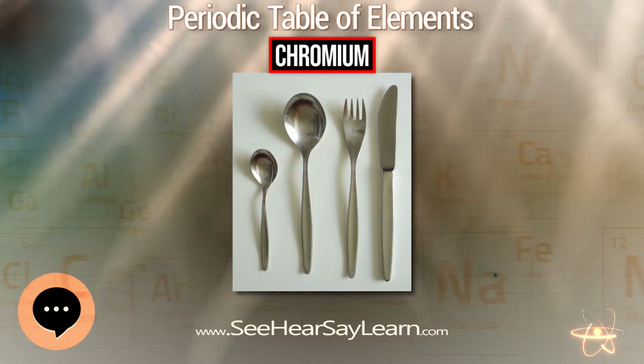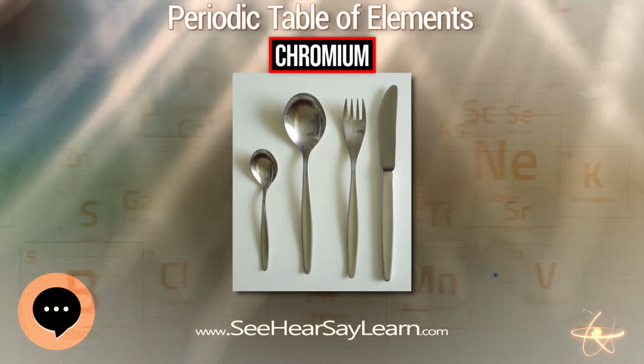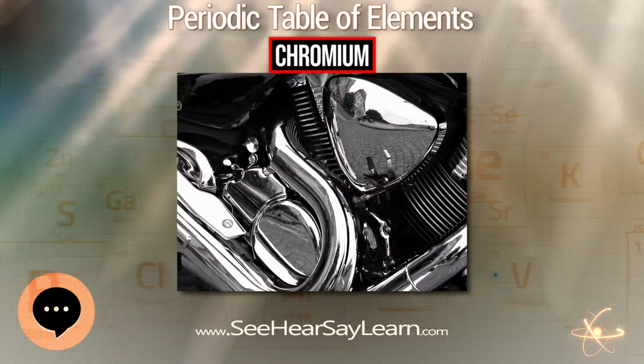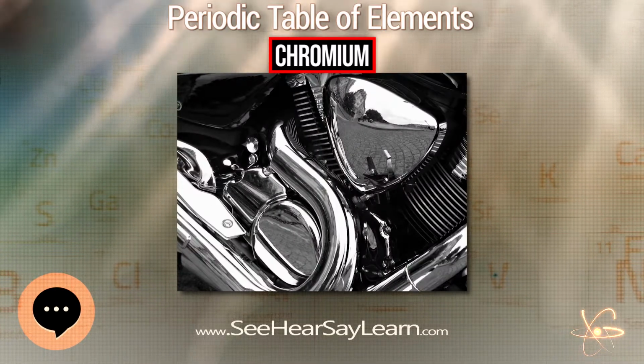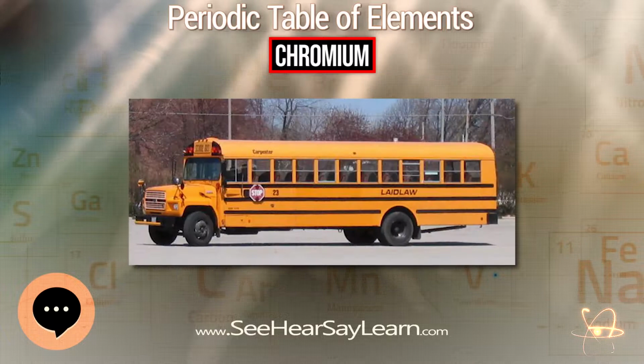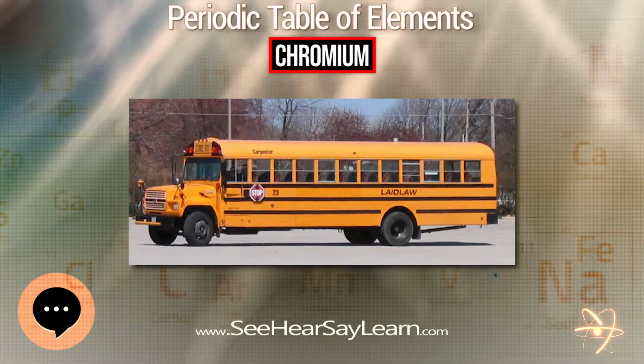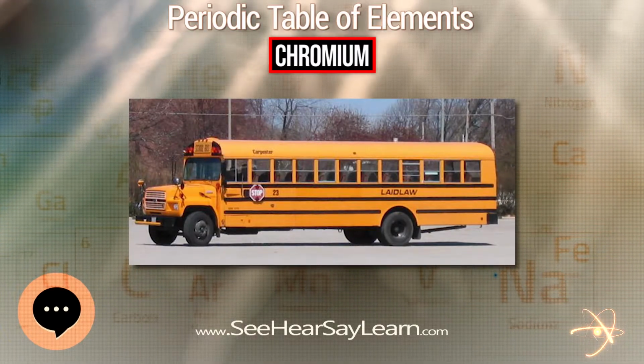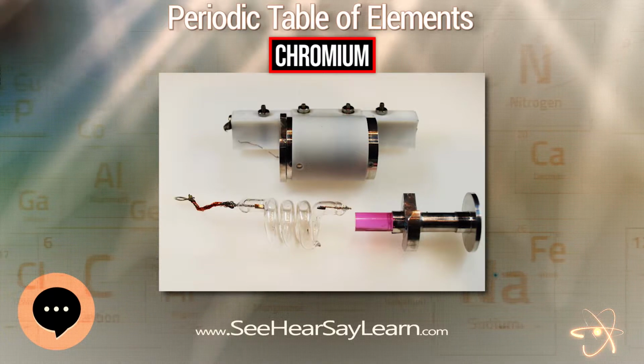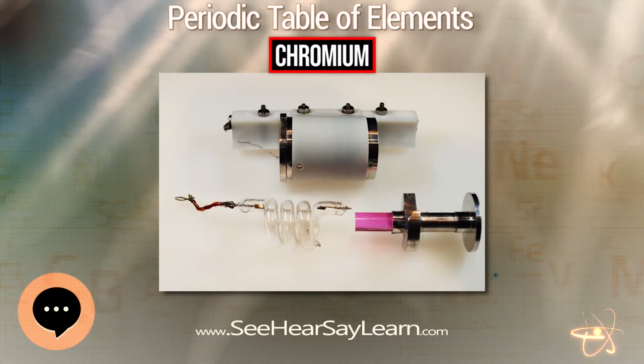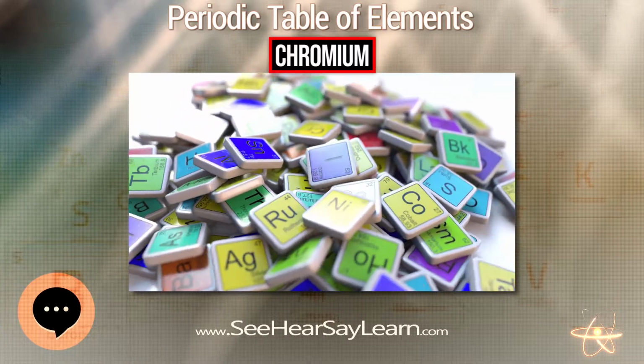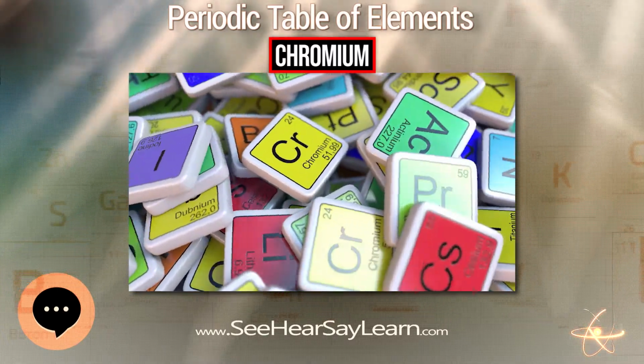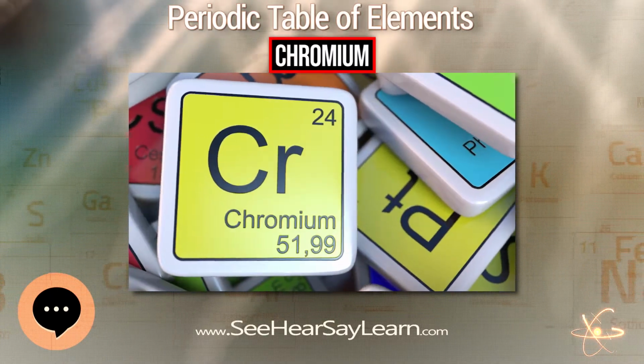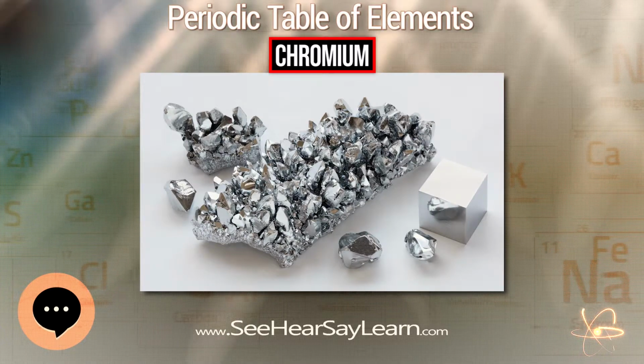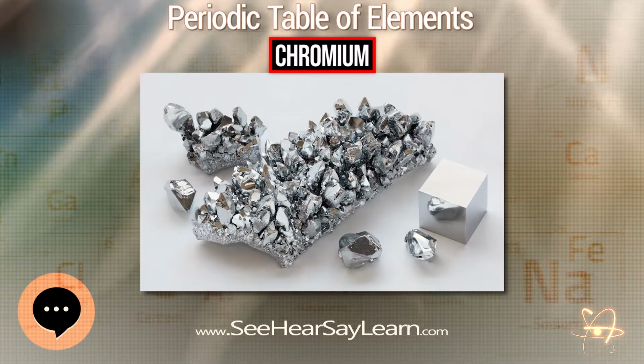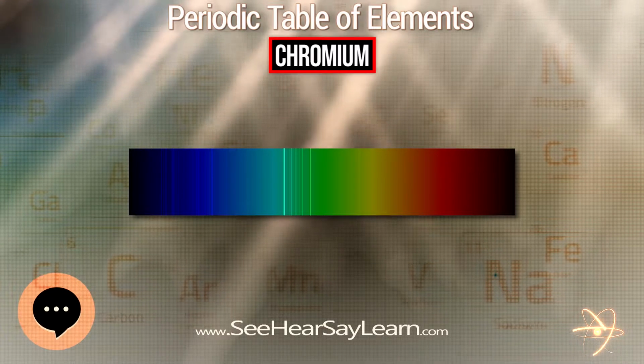The strengthening effect of forming stable metal carbides at the grain boundaries and the strong increase in corrosion resistance made chromium an important alloying material for steel. The high-speed tool steels contain between 3 and 5% chromium. Stainless steel, the primary corrosion-resistant metal alloy, is formed when chromium is introduced to iron in sufficient concentrations, usually where the chromium concentration is above 11%. For stainless steel's formation, ferrochromium is added to the molten iron.